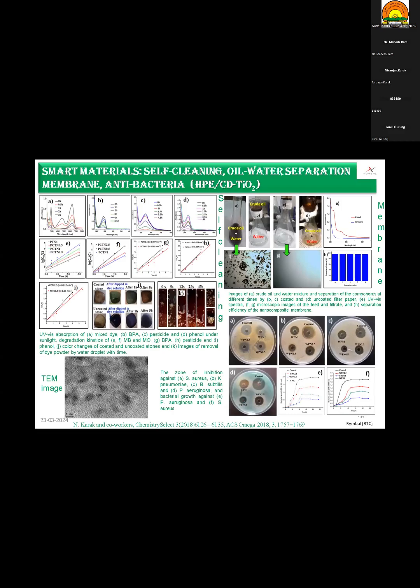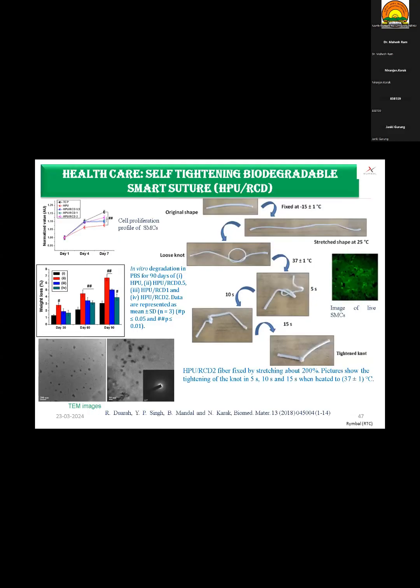If you incorporate titanium oxide along with the carbon dot, then the spectrum of applications will further improve. It will not only give you a self-cleaning system, it will also help to separate crude oil and water mixtures with the help of this membrane, resulting in repeated separation of water from oil. These are also biodegradable. There are other kinds of biomaterials we have synthesized using this nanocomposite system, like, as I mentioned, the smart suture, which can form a self-knot within 15 seconds at the body temperature of 37 degrees centigrade. These are also antimicrobial and biodegradable.